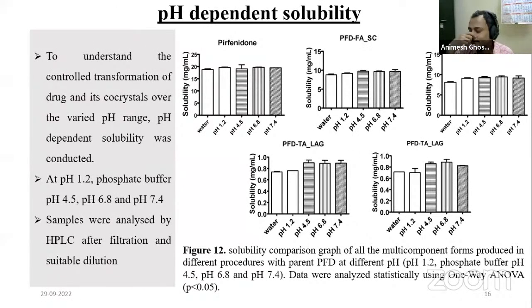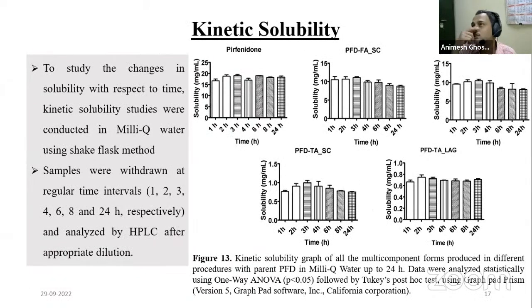Now, definitely we need to check the effect of pH on solubility, because our body has a gradient of pH from 1.2 to 4.5, 6.8, 7.4. So we started the solubility study at all the physiological pH, and it was observed that there is no significant difference at different pH. That means we can ensure that the co-crystal we got does not possess pH dependent solubility. Kinetic solubility means the solubility at different time intervals. We have studied up to 24 hours because our aim is to get the sustained effect of the co-crystal, and we could observe from this graph that it is almost similar, with no significant difference.